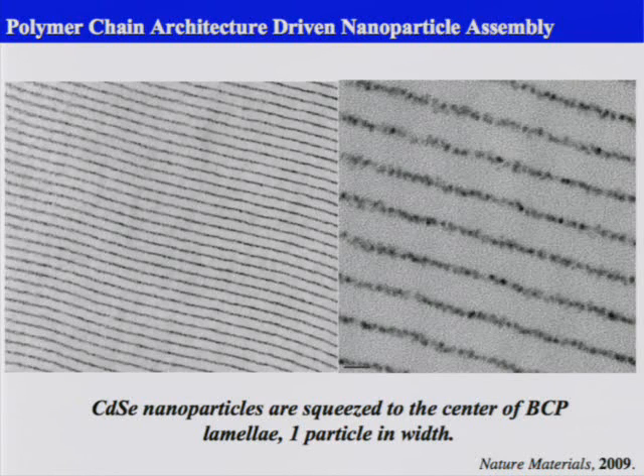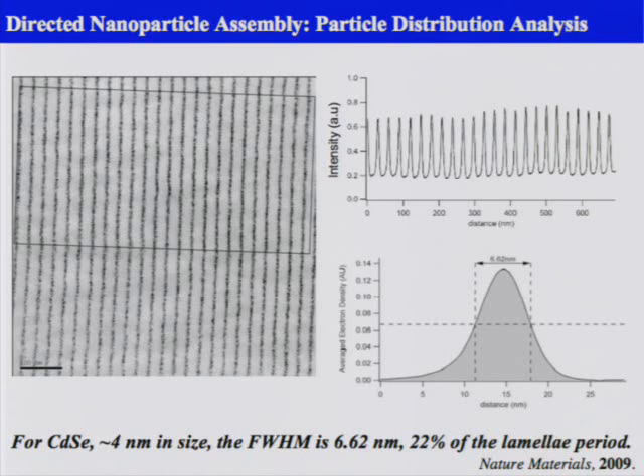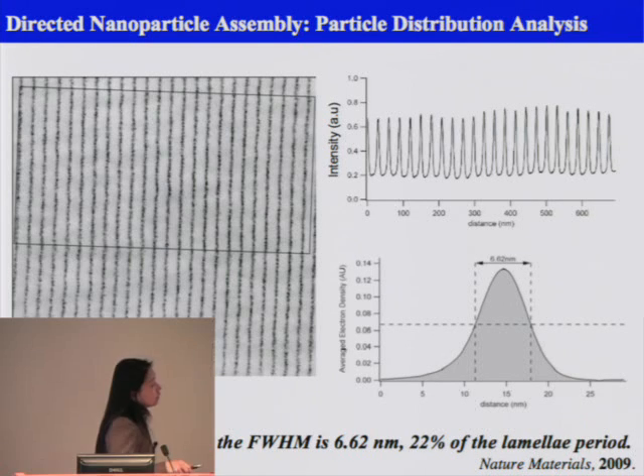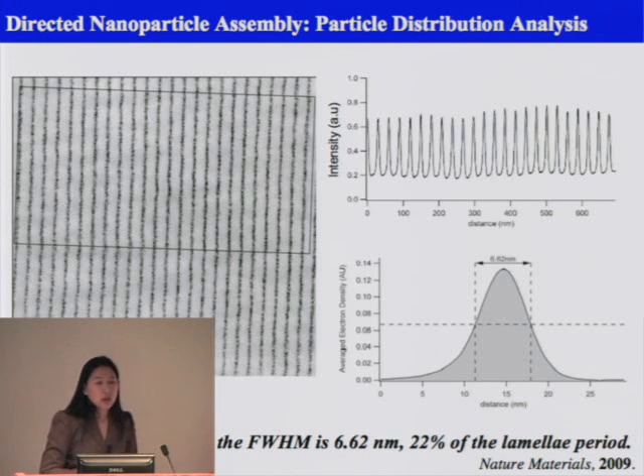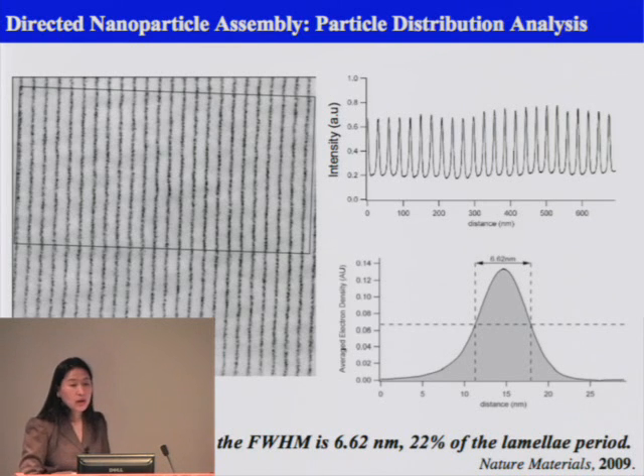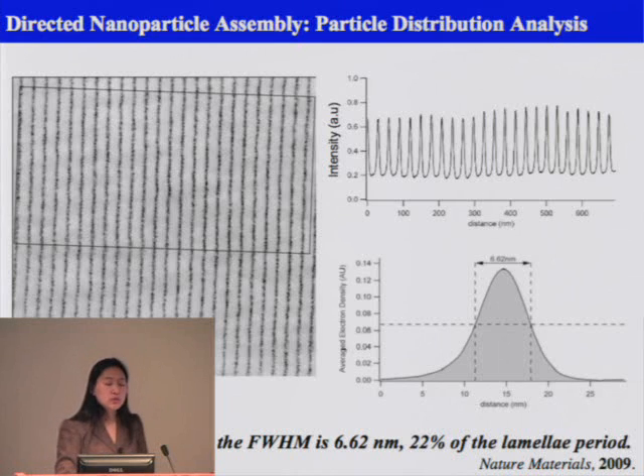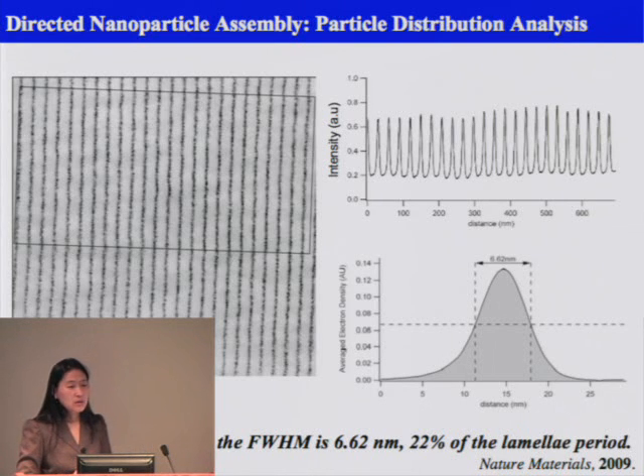You can see that the particle layer is only one particle in width - you only have this one sheet of nanoparticles in the system. If you do a TEM image analysis, what you see is essentially the electron density averaged out over the sample. For 4 nanometer nanoparticles, the full width at half maximum is about 6.62 nanometers, which means you can control the spatial distribution of the nanoparticle within a fraction of a single particle size, and that is pretty nice.